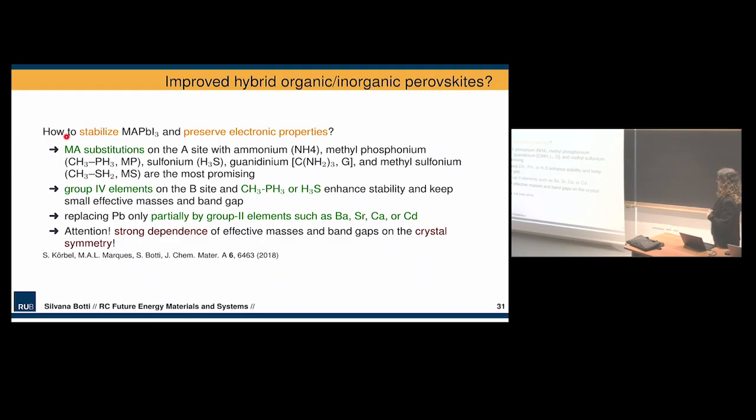the database. And so you see, for example, in this case, with this methylammonium lead iodide, we found interesting substitutions for methylammonium that could stabilize the structure a little bit. But we also found that the best way to go is probably to do some alloying, replacing lead only partially, because getting rid of lead was anyway creating problems either to the band gap or to the stability of the compound.